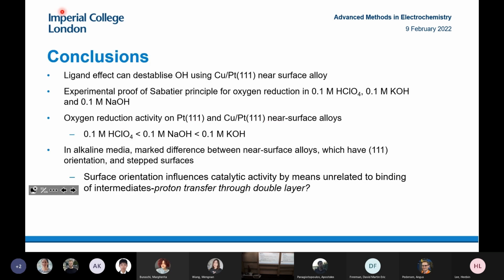So to conclude this first part of the lecture, I've shown that using an effect that had been previously predicted from theory but not actually elucidated experimentally, a ligand effect, we could destabilize OH using a platinum copper near surface alloy. And we use this experimental proof to prove the Sabatier principle for oxygen reduction in both acid media and alkaline media.